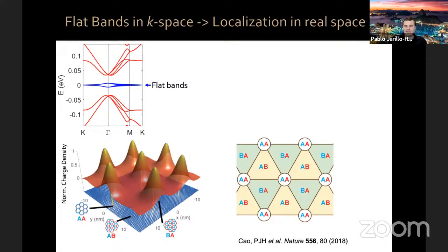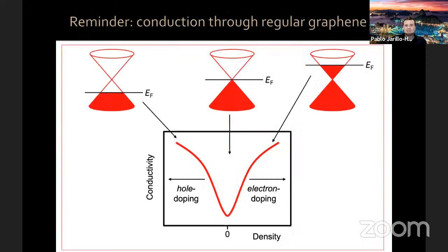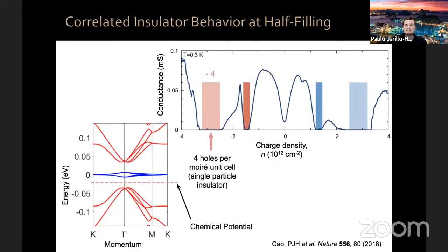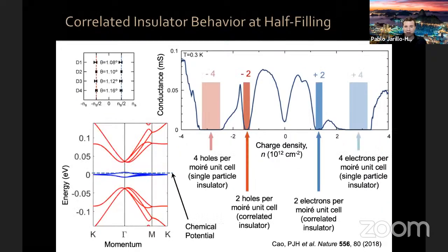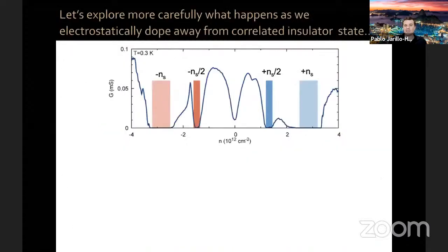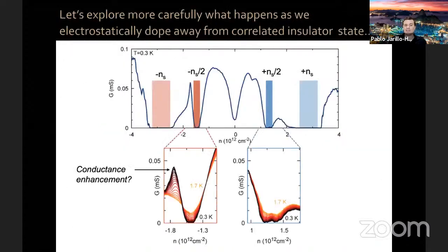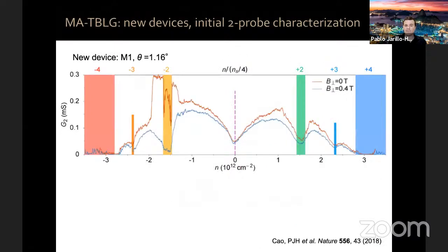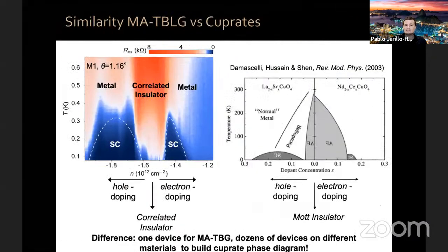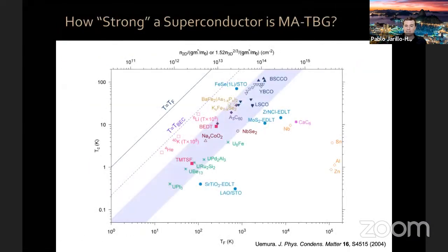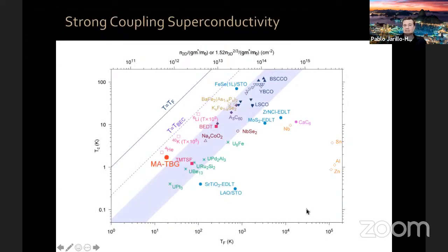There are people that believe that because we have a very high density of states in this flat band, perhaps the origin of the superconductivity is electron-phonon coupling, okay? Now, if that is the case, it would be extremely unusual because most of the conventional superconductors where superconductivity is due to electron-phonon coupling are in this region of the diagram.